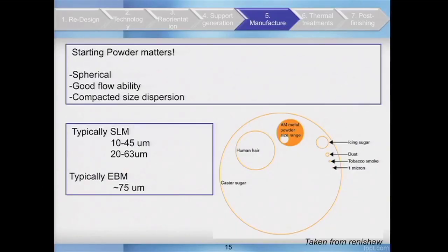some time of research. The powder that you will use it's important. Normally for SLM, the size is between 10 and 60 microns. It's important that the powder is spherical, and also the flowability of the powder. You need to really spread the powder well with your recoater in the machine. Electron beam melting is using bigger powder and plasma atomization techniques normally.